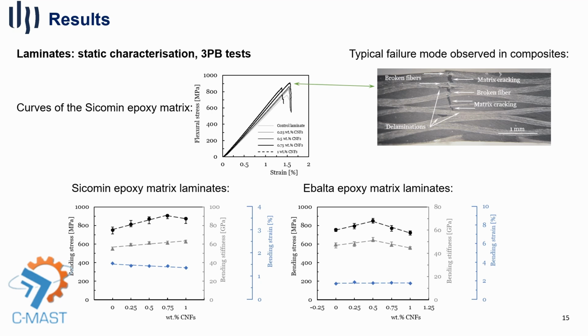Similar studies have been carried out on carbon laminates. Sicomin with 0.75% by weight of carbon nanofibers increased bending stress by 20.4%, from 752.2 megapascals to 905.3 megapascals. The stiffness increased 11.4% and the deformation decreased 3%.